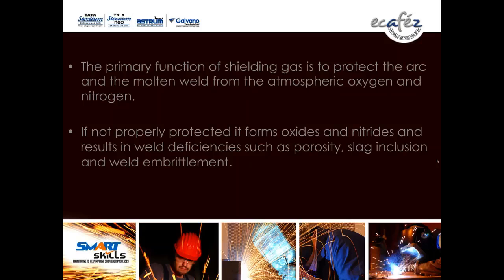The rate of gas flow in CO2 should be around 15 liter per minute if you work within the workshop area. If you use the CO2 in the exposed area, you should go for 17 liter per minute. But CO2 will not give you good quality weldment, except there is less spatter in CO2 and the penetration depth will be more. That is two advantages of CO2. But if you go for argon CO2, you will get very good quality weldment for your job. Next.